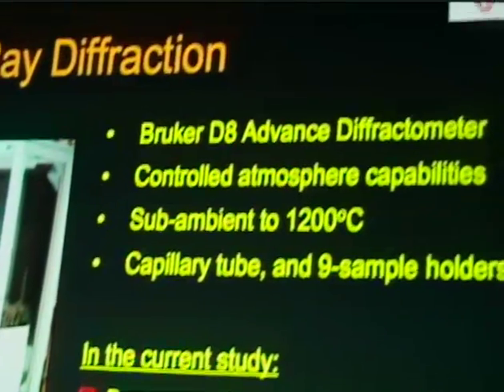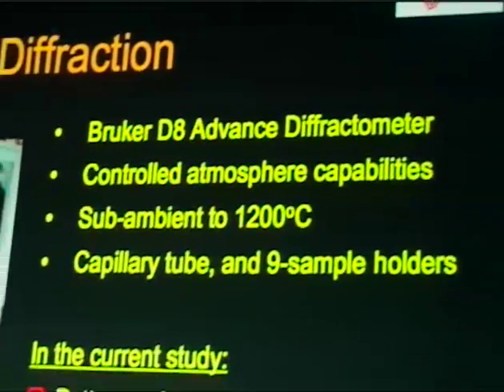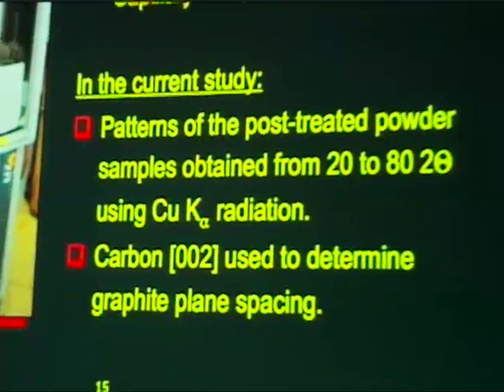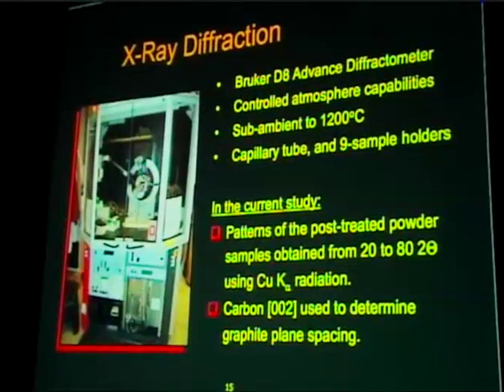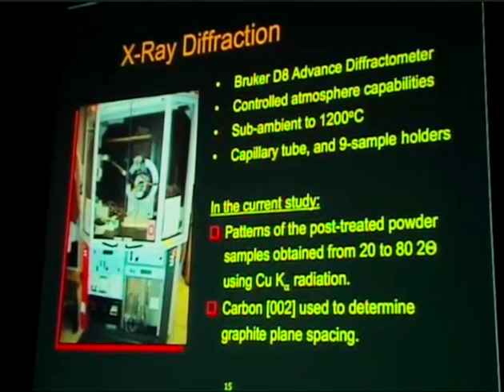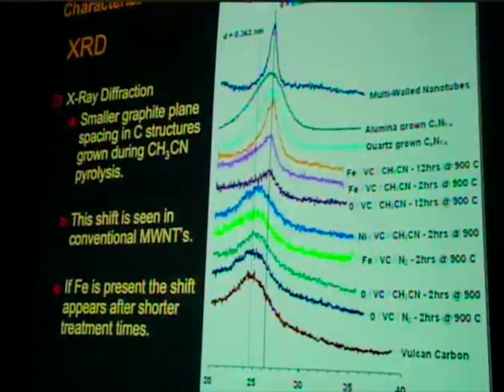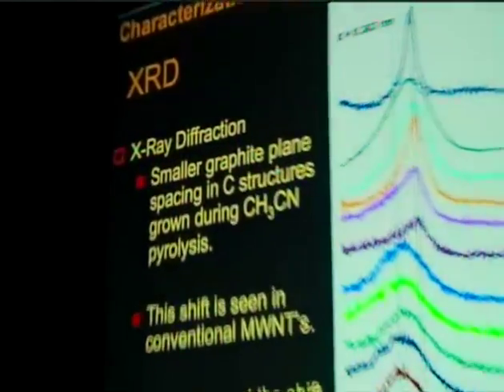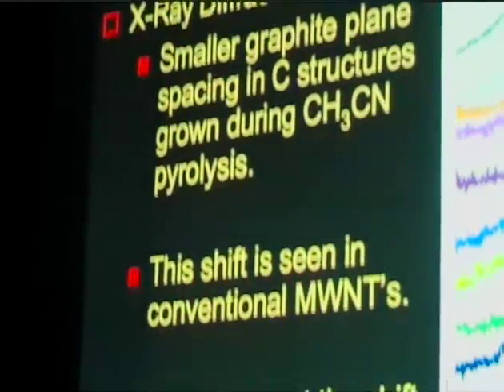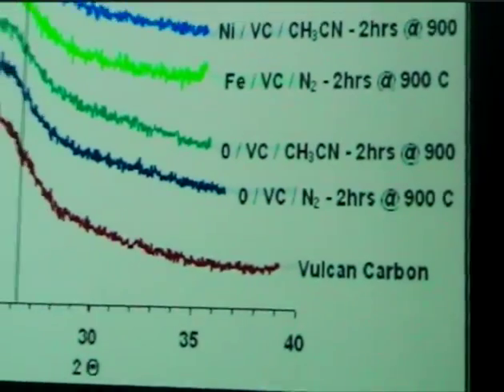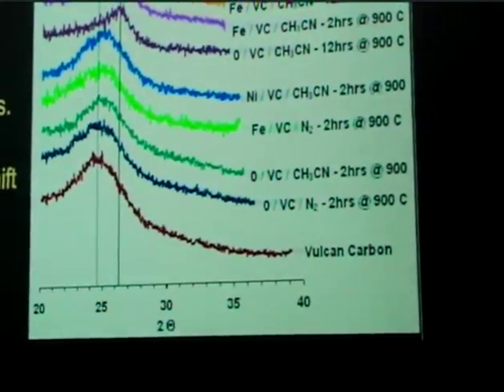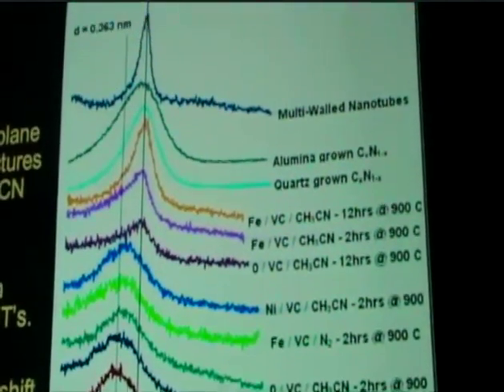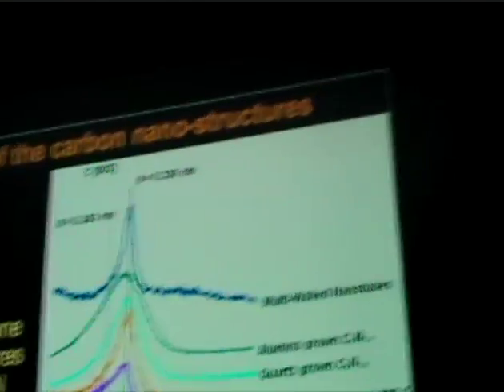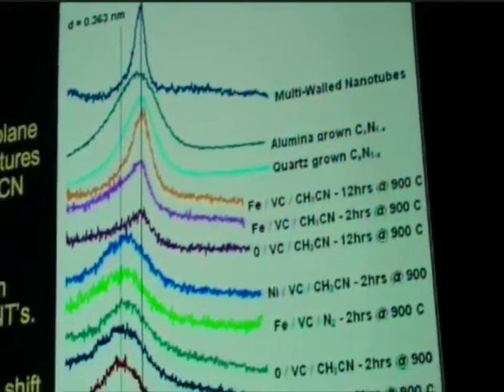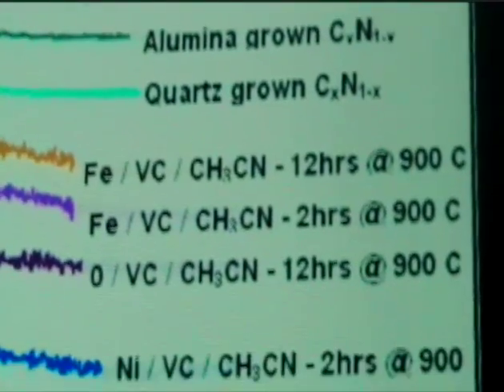Now, if we look at the X-ray diffraction, we have an in situ X-ray diffraction system where we can go from cryogenic temperatures to 1200 degrees centigrade, pretty much in any atmosphere that we want. Here is the X-ray diffraction pattern for Vulcan carbon. As we go through these materials which have gone through the acetonitrile treatment, we end up with smaller graphite planes in the carbon structures. These are structures grown during the acetonitrile treatment.